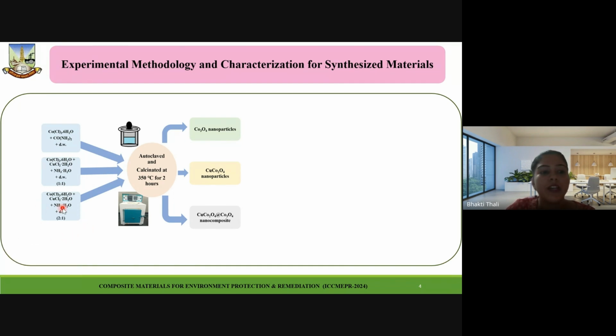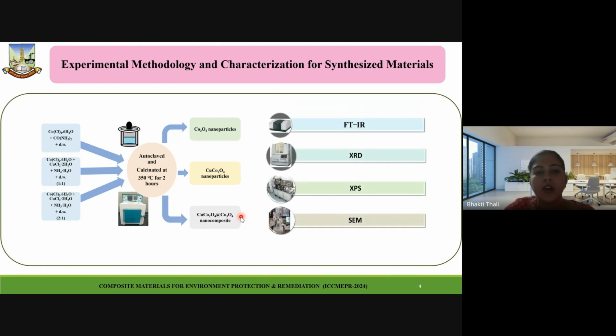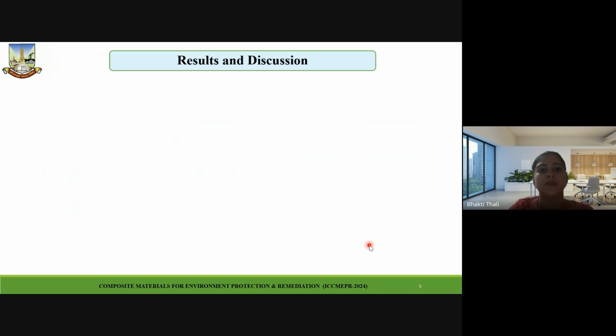Thirdly, cobalt chloride, copper chloride, ammonia water along with distilled water in the ratio 2:1 was subjected to autoclaving and calcination to obtain the final hybrid copper cobaltite cobalt oxide nanocomposite. Further, all the three materials were confirmed by techniques such as FTIR, XRD, XPS, and SEM analysis. Now I'm going to focus on the results and discussion part.